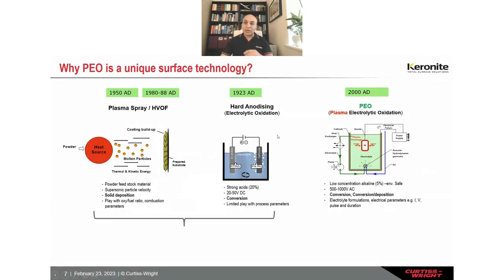On the middle one, you have again a very well established technology, nearly a century old, hard anodizing, used in many applications, but for moderate to non-severe applications. How is the process done? As the name says, anodizing, the part is made an anode in an electrolytic cell, and a DC voltage is applied. And you can see the hard anodizing is done primarily in strong acid-based solutions. And that's one of the key drawbacks, because it will have some environmental effect.